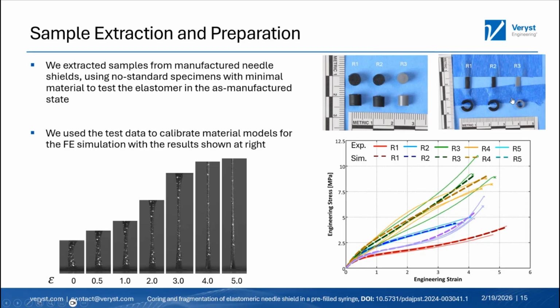In the lower left, you can see snapshots of the test that we ran at 4 or 5 different strain levels. We use a method called digital image correlation during these tests, where we take thousands of images during the test and post-process them afterwards to extract the strain that we apply. And so we get these images, which is a great record. You can see this huge stretch that these materials undergo before they get to failure, up to about 500% strain or more. Over on the right, you can see the results from those tests.